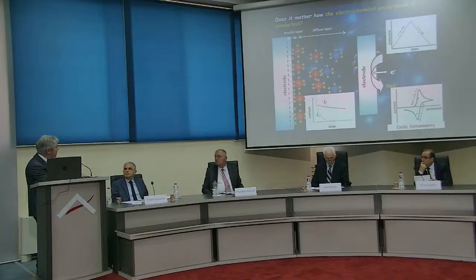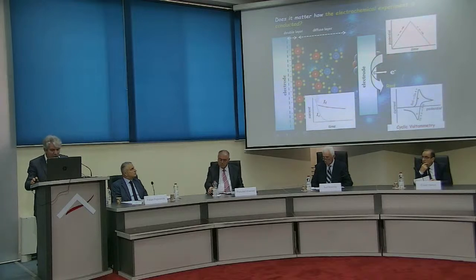But if we look at the microscopic structure of the phenomena, for any external application of the potential at the electrode surface, not only electron transfer takes place, which is the desirable phenomenon in batteries, in electroanalysis. But any externally applied potential at the electrode surface, of course, causes tremendous variation of the full environment close to the electrode surface. And then the supporting electrolyte, of course, responds accordingly, and a sort of current is flowing in the system just because of formation of, we say, the electric double layer, and that current is called charging current. Our idea is to measure the Faradaic current, real electron transfer, but always both currents flow.